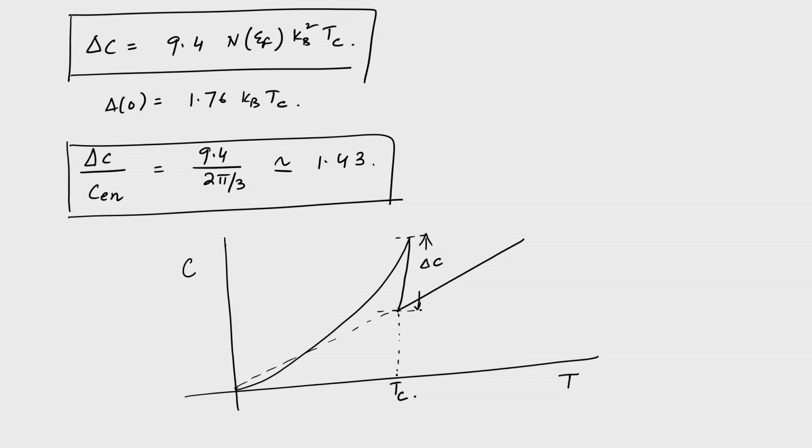So, basically this is a hallmark signature of a second order phase transition. You see that these two values, just below Tc and just above Tc, as you increase the temperature, the specific heat acquires the same value, and this is due to the fact that the latent heat of course is not there, and it is a feature of a second order phase transition.